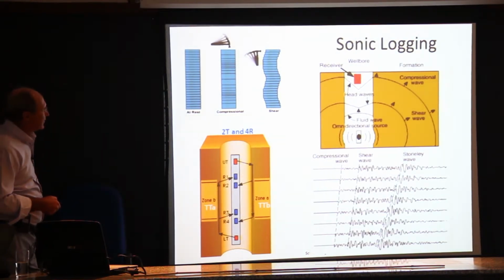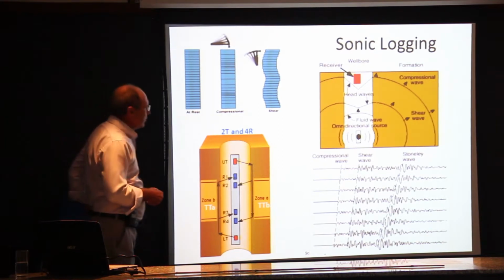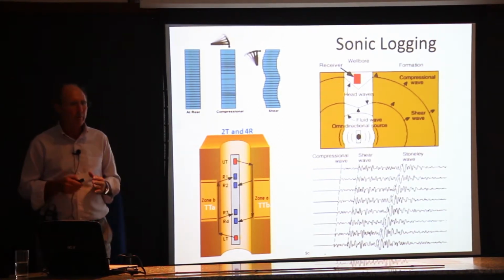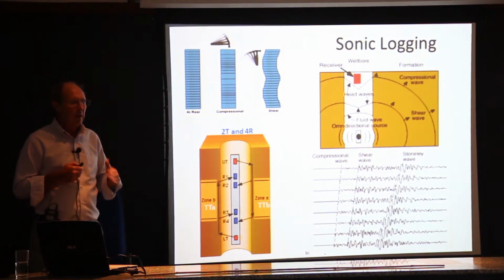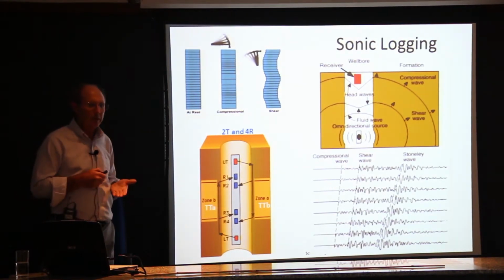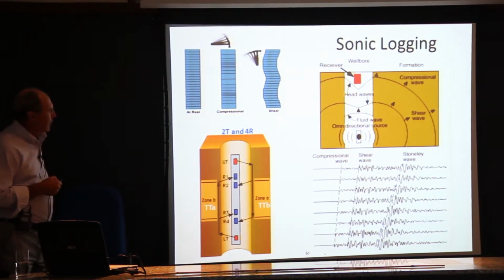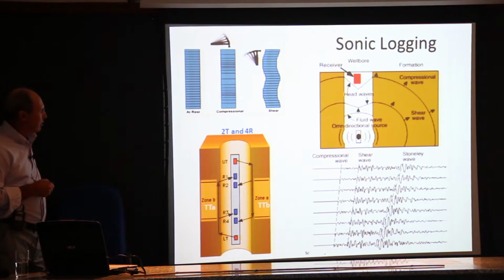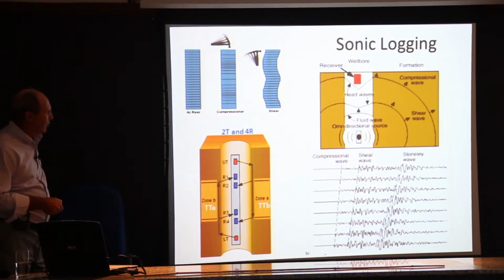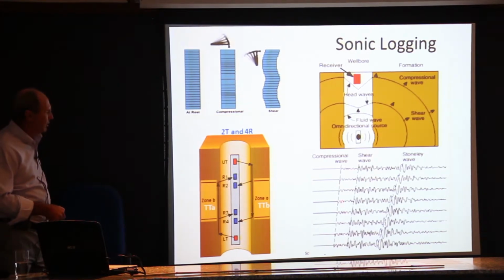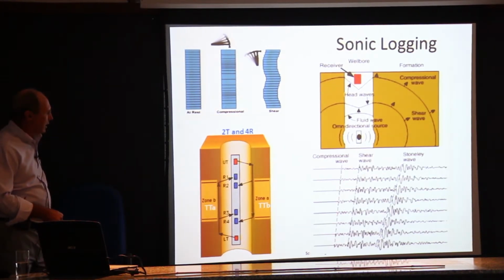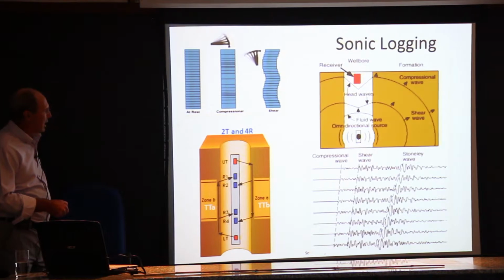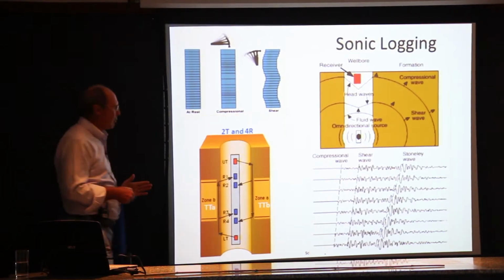Now acoustics, not used extensively for formation evaluation in the pre-salt. Acoustics is normally run in particular to help tie into the seismic data. But we're using it more and more to help with the formation evaluation. With acoustics, there are three modes that we're interested in. The P wave, or the compressional wave, which is most useful for indicating porosity and also for tying into the seismic data. The shear wave, also helpful for tying into seismic if you have good shear wave seismic, but is very, very good for indicating fractures as well.